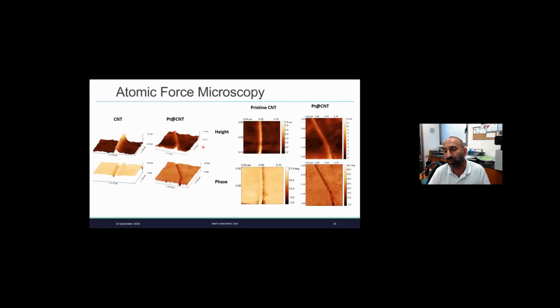By AFM, we also prove that it's not on top of it because we have some phase and height image of the AFM. And what you can see is that when we have one platinum here on the kink, we don't see any difference in the height of the nanotubes. So it means that the platinum can't be on top or below, it has to be in.